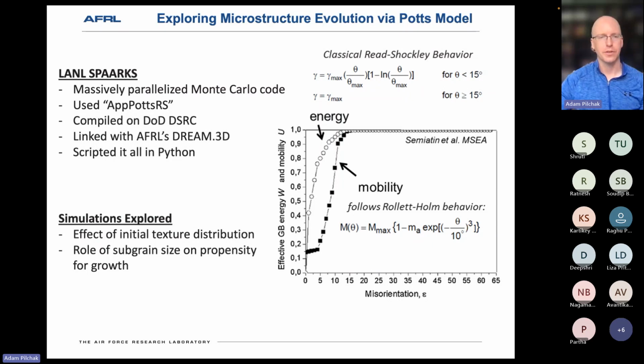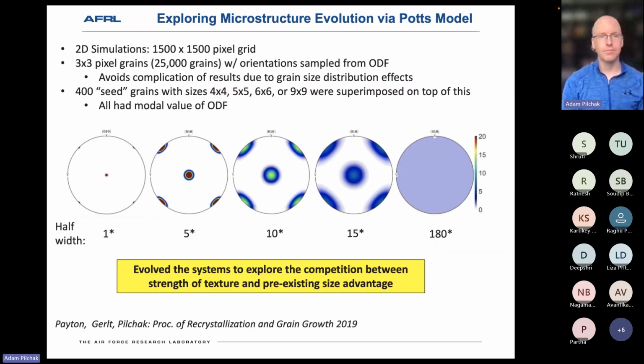distribution of texture, so the width of the texture components, and we'll see that on the next slide. But then also investigate what's the role of subgrain size on the propensity for those grains to grow, essentially trying to understand if certain subgrains had a size advantage relative to their neighbors, would that make them grow, or was this entirely driven by grain boundary energy?